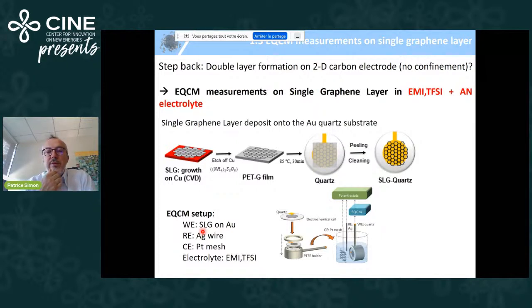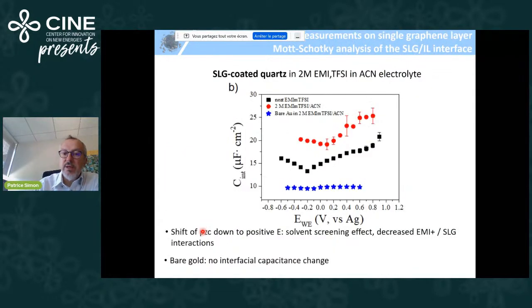And I'm going to show you now results with EMI TFSI dissolved in acetonitrile. So the same thing, except that we added some solvent to the EMI+. And this is the change of the interfacial capacitance, for what we just saw, the neat EMI TFSI, the V-shape plot I presented, and the same for EMI TFSI, 2 mol per liter in acetonitrile electrolyte. And here, this is the bare gold quartz. What you see first is that the minimum, which corresponds to the PZC, the potential of zero charge, is shifted from negative to positive potential values when you add solvent.